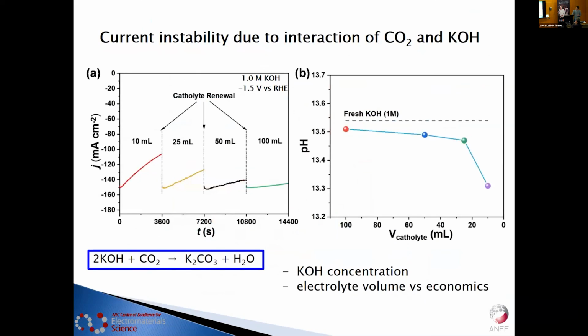But what we found is a problem if you want to maintain current stability. There's an issue with the interaction between the KOH and the carbon dioxide, so they form potassium carbonate. Imagine you have 1 mole of CO2, and it will react with 2 moles of KOH, so you have just 50% left for the real CO2 to react. So there's what they call carbon loss in the reactions. So to maintain the high currents, we have to use a high volume of electrolyte. And the question now is the economics of the reaction, whether it's economic, right? And of course, you might ask, instead of 1 molar, why not use 2 or 3 molar? But we found it's not stable for this catalyst. So that's another challenge.